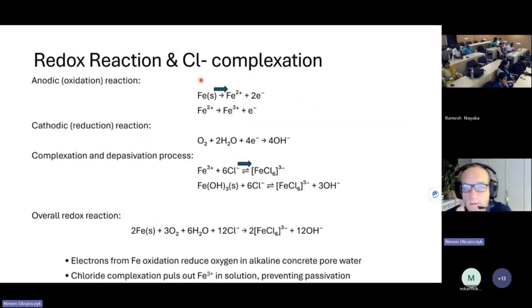So a little bit about the redox reaction. This is actually linking to the first day with the chemistry, why we have this complexation reaction, if you remember. So basically, why is steel passivated? Because we have the high pH, and that makes the iron hydroxide layer on top of the steel, which protects the steel from corrosion. So this is the passivation of the steel at high pH. So that's why we also need high pH, because we want to create this passivating iron hydroxide.